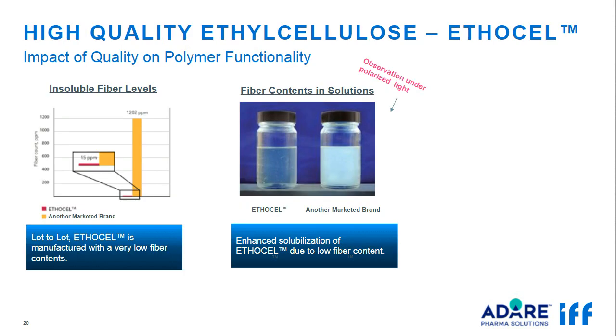Quality of Ethocel in any application is critical for a robust performance and reproducible result. Unreacted cellulose fibers from ethylation reaction during manufacturing could be problematic. Ethocel has lower insoluble fiber content as compared to other ethyl cellulose brands in the market, 15 ppm in Ethocel versus about 1200 ppm in the other brand of ethyl cellulose. High level of insoluble fibers would result in producing films with poor quality, which can cause premature drug release, adverse effects, or the need for excessive coating rates to obtain reproducible results.